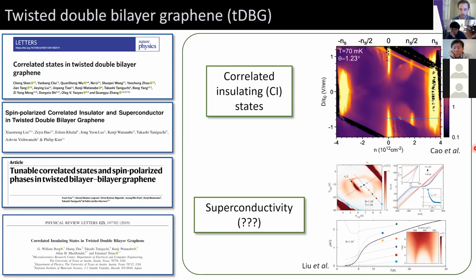A number of groups noticed that if you slightly detune from the half-filling correlated insulating state and measure the device resistance as a function of temperature in this halo region, you see something that's roughly linear in T down to some low temperature of around 6 Kelvin or so, and then it abruptly drops towards 0. Maybe it hits exactly 0, maybe it doesn't, but it's something at least suggestive of a superconducting transition.